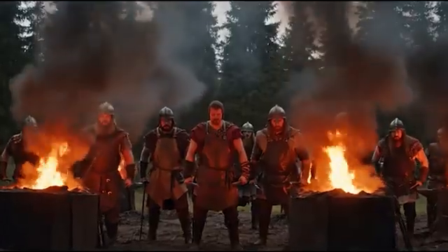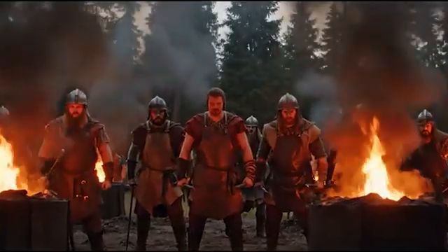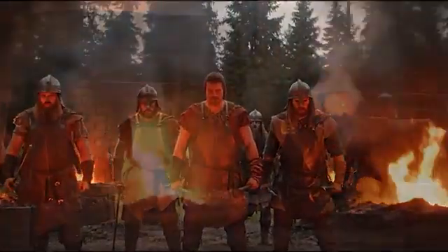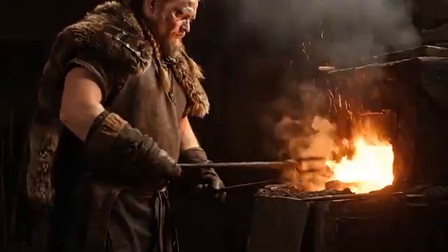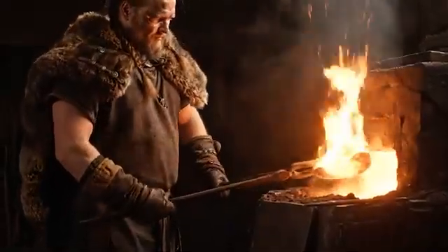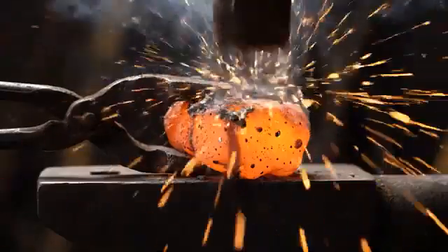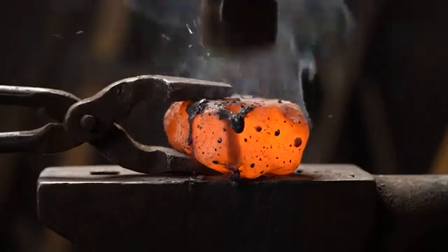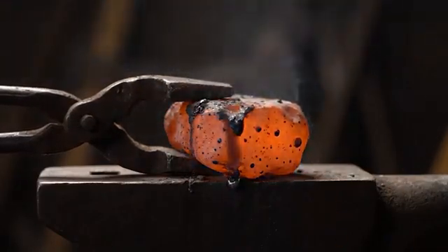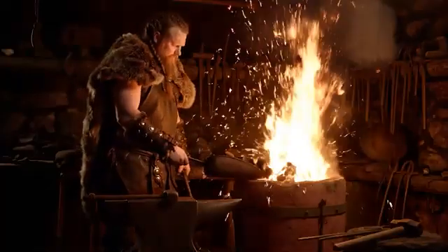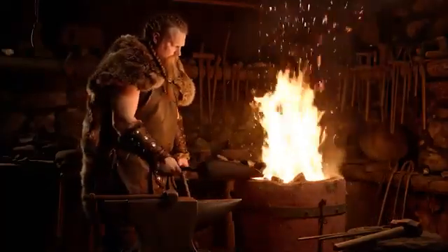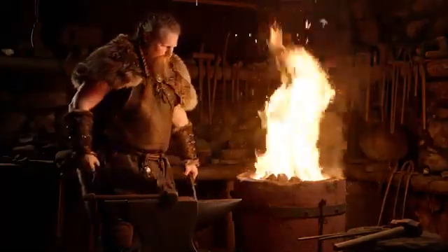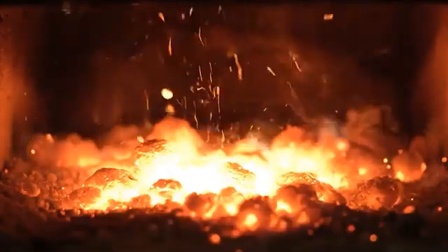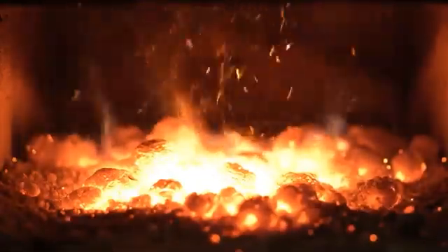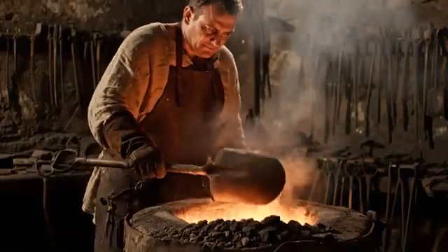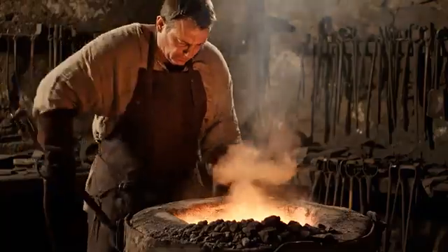Are you ready for the shocking truth about what was actually extracted from the smelting furnace? It was not liquid metal, as in modern blast furnaces. The wet smelting process produced a lumpy, spongy piece of iron saturated with slag, which was called a bloom. The smelting process began with loading charcoals into a preheated furnace. When the coal burned to the desired temperature, the master began to alternately pour layers of crushed ore and coal.